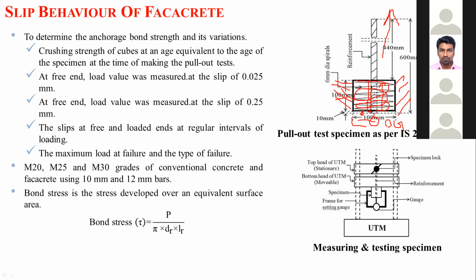That is, the load is the load which we apply to pull the reinforcement out, that is P, and area means the corresponding area which the reinforcement is surrounded, that is pi d L. D means the diameter of the reinforcement, and L is the depth up to which the reinforcement is inserted. So we used this test in the UTM.